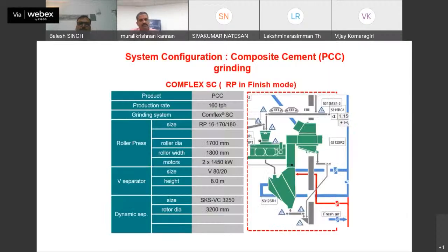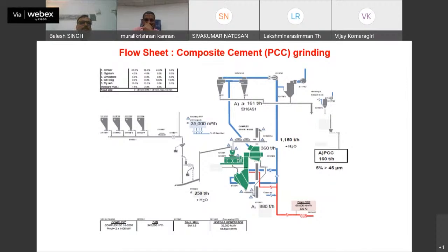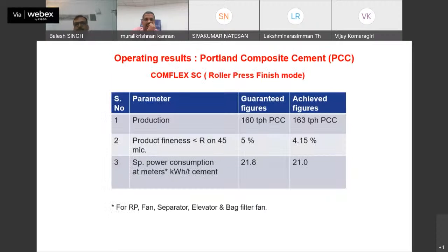So one example I'm sharing is from Bangladesh, where a roll press circuit was supplied with 160 TPH guaranteed, and it was for clinker, gypsum, limestone, slag, fly ash. These all were constituents. So it is working all together, and the production was guaranteed at less than 5% on 45 microns, which was very much achieved. And the plant is running successfully at 163 TPH, which was given during the performance test. So you can see the product fineness is less than 5%, that is 4.15%, and power was 21 kilowatt only.